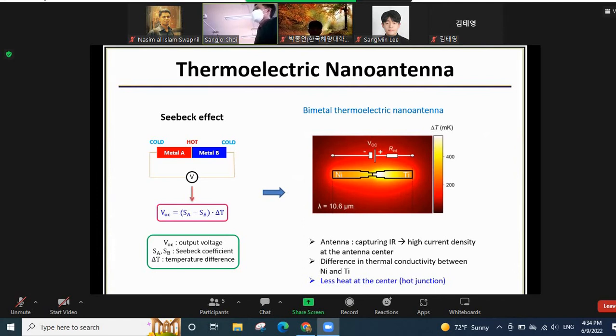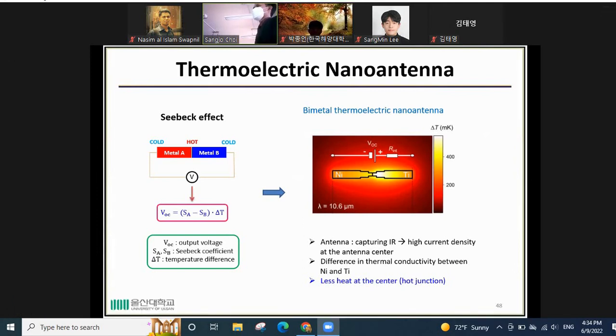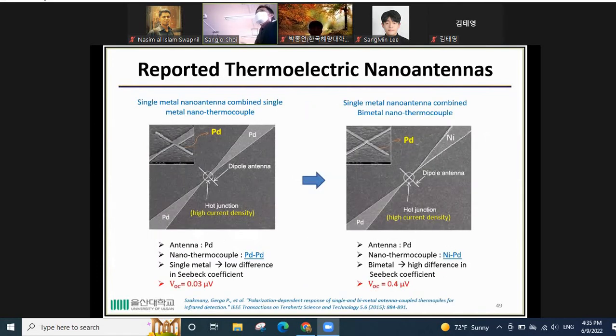However, we can see that less heat happens at the antenna center because of the difference in thermal conductivity between nickel and titanium. So, to maintain the high temperature at the antenna center, people use single metal nano antenna to reduce the heat transfer from the first to the second antenna arm. So this is the single nano antenna combined with the single metal nano thermocouple. You can see that this antenna is showing 0.03 microvolts VOC. This VOC is small because the single metal shows a low difference in Seebeck coefficient.